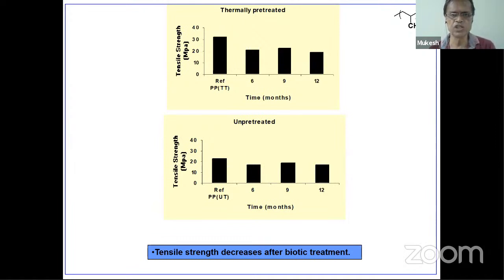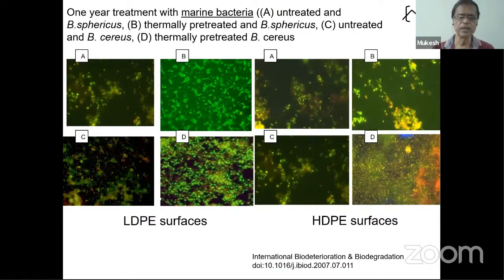This gives you some changes in the tensile properties as well, as you can see here. Tensile strength keeps going down as a function of time, over a period of 12 months. This picture shows you bacterial attachment on the surface of different types of polymer, low density polyethylene, high density polyethylene. And as I mentioned before, green color indicates live bacteria, red color indicates dead bacteria.